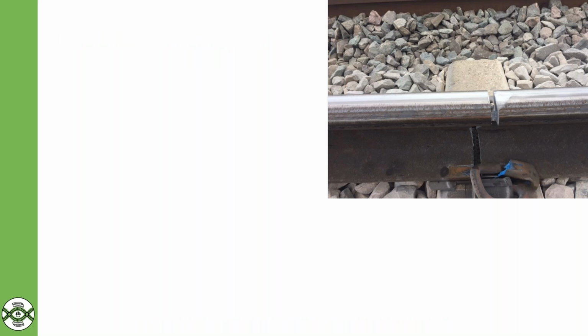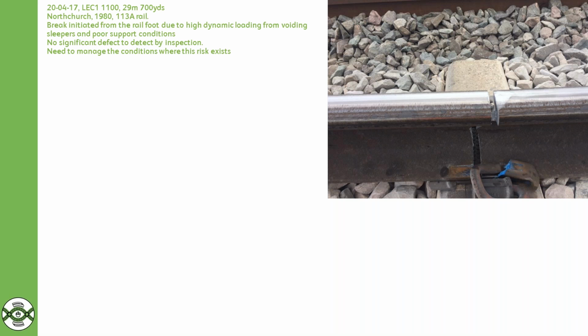Another example here, this one from the West Coast main line, typical foot failure, straight over a sleeper. Fortunately, it all stays lined up on the sleeper, which is good. But when we looked at this one, again, a lot of voiding. You can see in the picture around the sleeper, the edges of the sleeper very badly worn. So it's clearly been moving in the ballast for quite a time. And what's not shown in this picture, again, this is a transition to a structure, but a common theme where we've got poor support conditions.